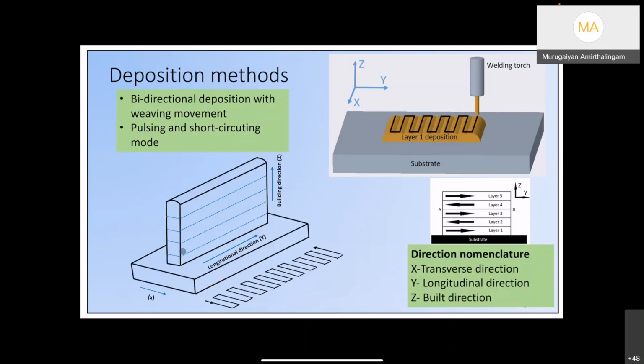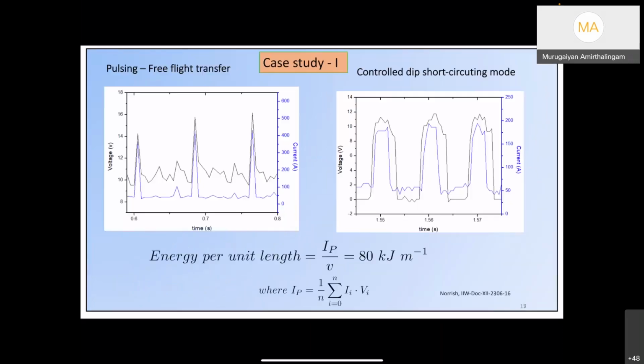In additive manufacturing, we deposit layer by layer. Along this X direction, we move the torch. We weave it, in welding terms, in the X direction, and then one bead is completed, and then we come back from here and go here, and continuously we can build, say, a thin wall deposition. So what happens?